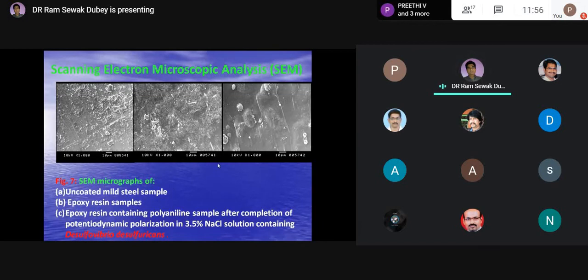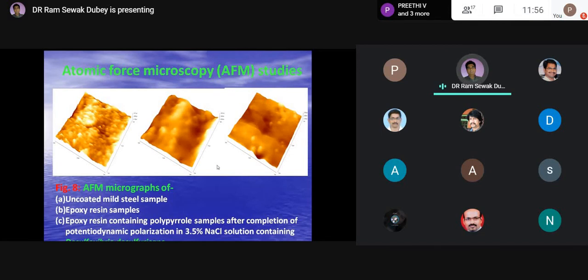Further, atomic force microscopy was used to ascertain the interaction and adhesion of microbes onto the metal surface. And it is also clear here, the first one is the uncoated steel sample, second with epoxy resin, and third one, a similar sample containing polypyrrole. It is observed in the last one, AFM, that the sample is very smooth and there is almost uniform deposition of the polypyrrole onto the metal surface.